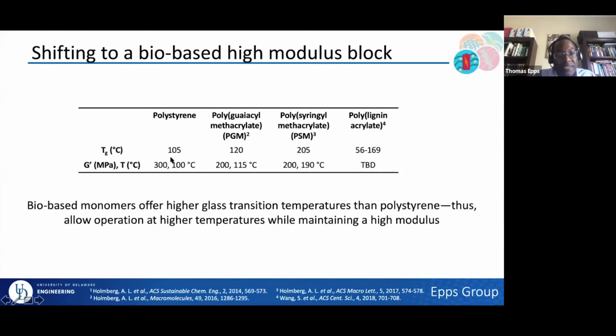And one of the nice points is that you can say we lose a little bit in modulus, but I would say that for many applications, this 200 to 300 megapascal range for these materials at 100 or at 115 degrees is going to be quite useful.